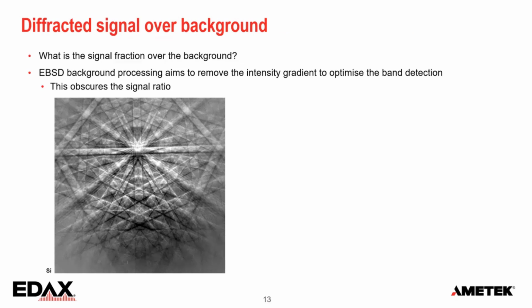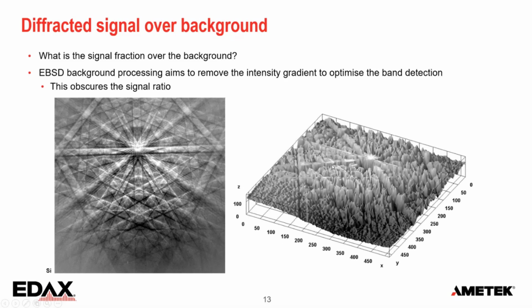So what is this signal fraction over background? Can we quantify that a little bit better? And here we see a silicon pattern, background corrected as we normally do when we work with EBSD, and that really obscures the signal ratio. When you plot this in a three-dimensional plot, you can see the intensity gradient, of course, is gone, and we have a lot of spikes everywhere. And that's all the details that we see in these bands that we can just make out. We can still see all the bands very nicely. We can index this, but we can't really judge the background to diffraction ratio.